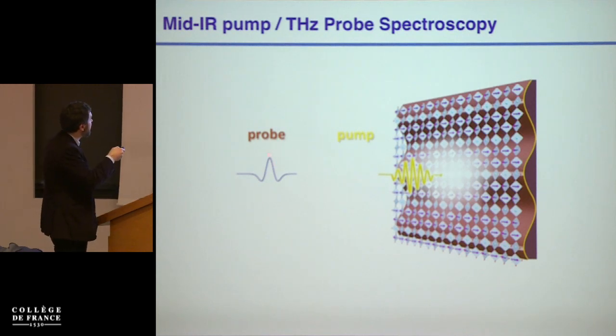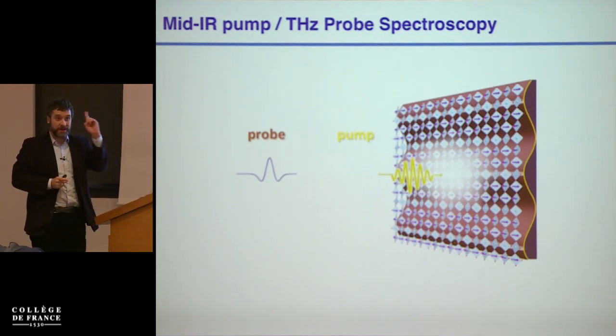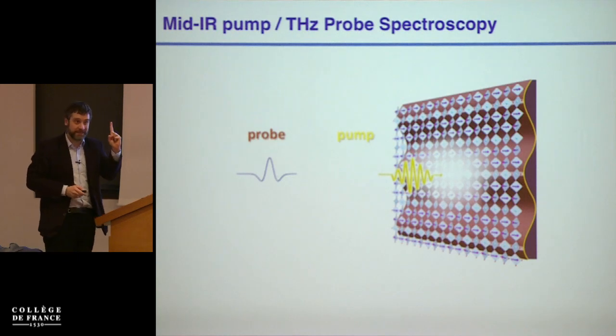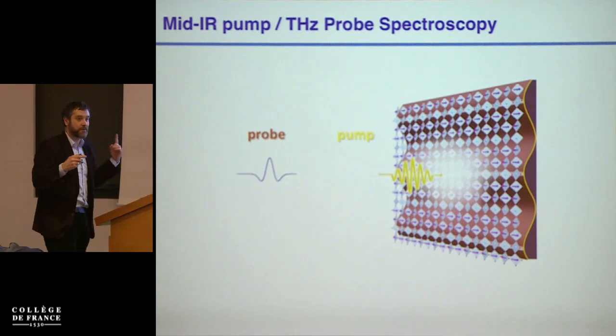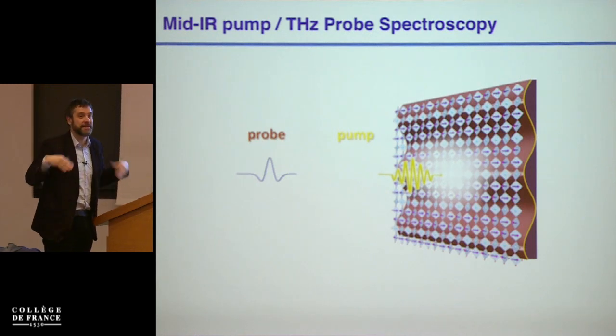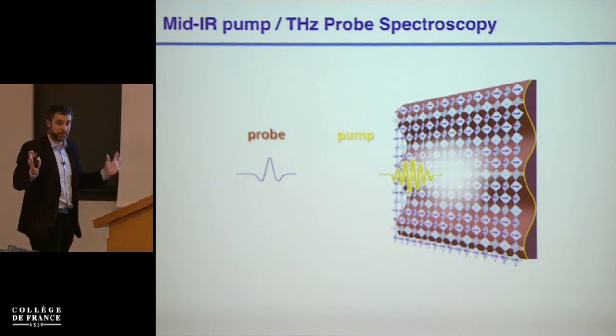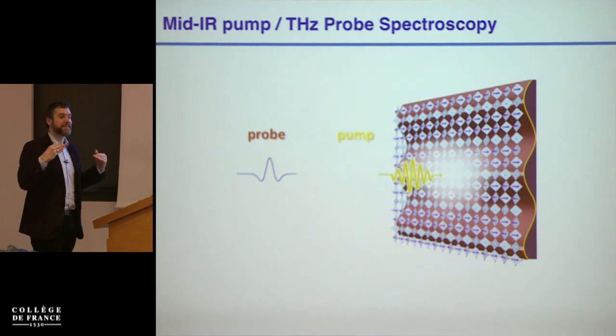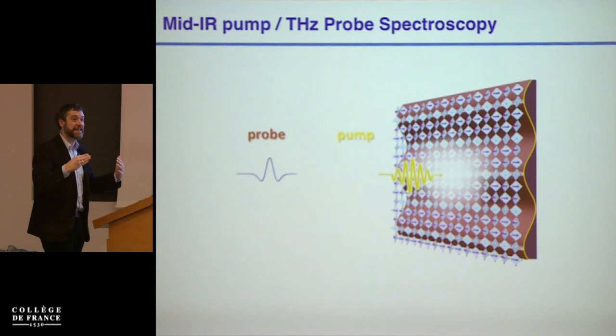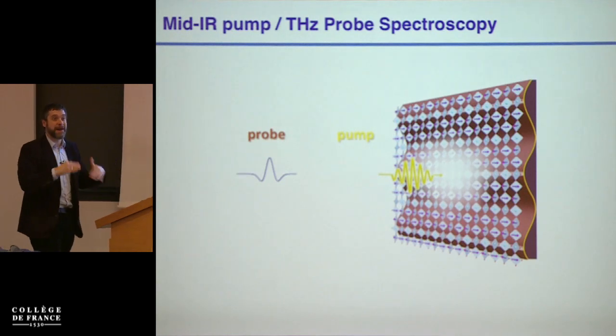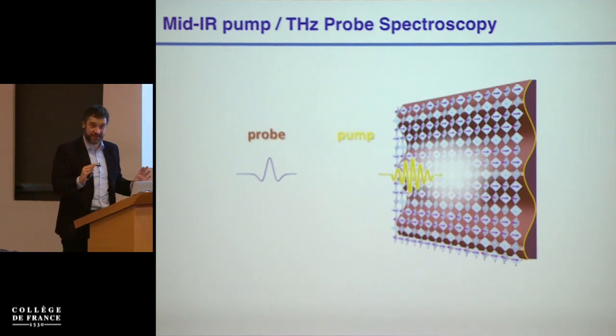And then I will come with a second probe pulse, which will probe the reflectivity perpendicular to the planes in a system that at equilibrium does not have a plasma edge because I'm in the normal state, and I'm going to hope to see the appearance of a plasma edge. This is the protocol. And I'm going to say that if I see a plasma edge, I can at least write a paper where I say that I have seen the formation of a superconducting state by melting of this stripe order.